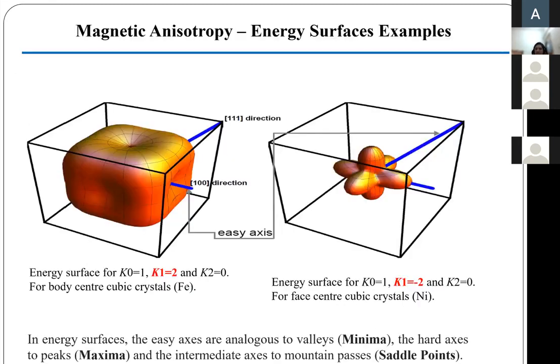And this is where the definition of easy axis also comes through very nicely. When I plot the magnetocrystalline energy, there are clear minima. In this case, for this combination of material constants, assume that this is non-dimensionalized, so we can play around with these values. So we can see that for this combination, there are minima along 100 directions, right?